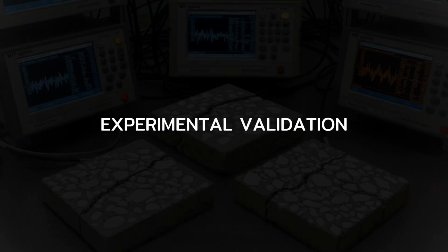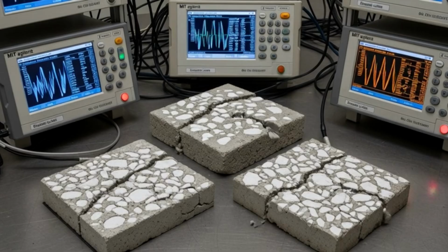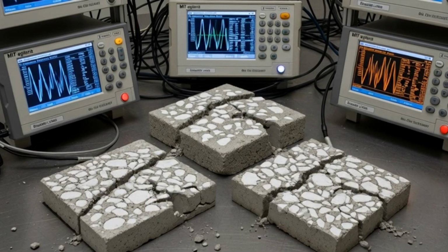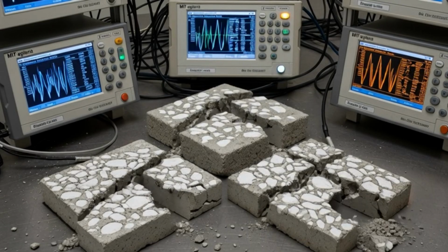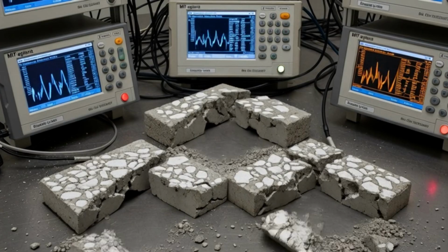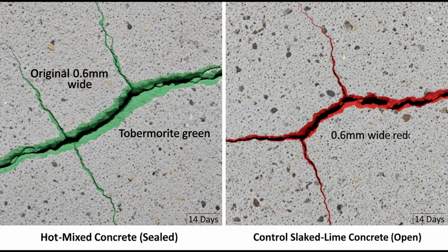Experimental validation. The MIT team created concrete using the hot mixing method, incorporating quicklime directly to create lime clasts. They induced cracks, exposed the samples to water, and monitored healing. Result: cracks up to 0.6 millimeters sealed completely within 14 days. The calcium carbonate precipitation filled the gaps. Control concrete made with slaked lime only kept its cracks open, with no healing observed. The lime clasts are the key. They're a distributed repair mechanism embedded in the material.